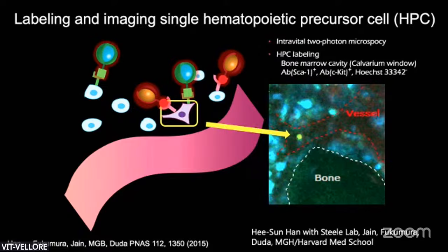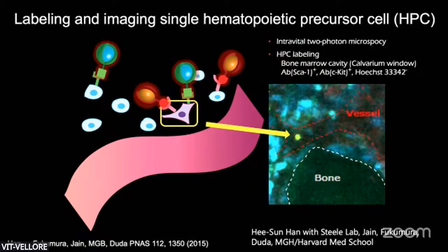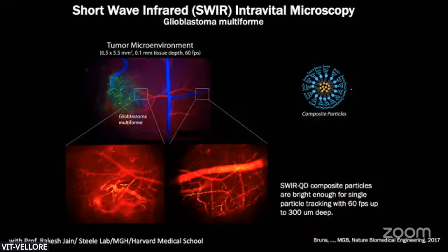And then you can start to study its microenvironment and understand a little bit of biology. One of the things that we also discovered was that the color of these dots depends not only on the size, but also the composition of the material. So by changing the composition, by going, let's say, from silicon or cadmium selenide to some other semiconductor, in this case indium arsenide, we can make light that's further into the infrared and with still fairly good efficiency of emitting light. And then we could use that in biology because organic molecules have very poor emission in that color.